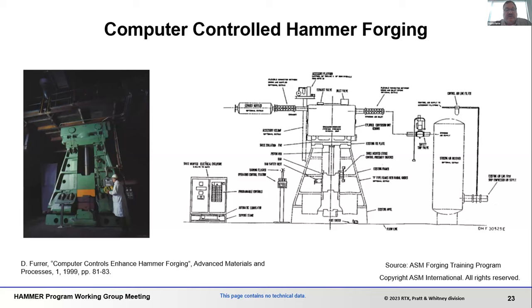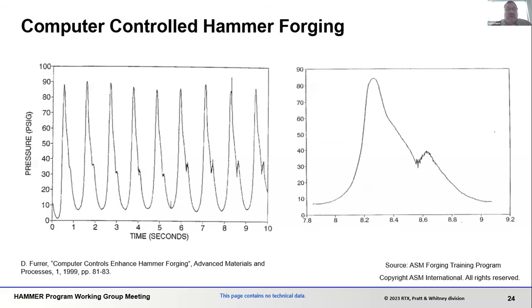But one of the main reasons is to control temperature, right? So now you can start to forge and incrementally control the amount of adiabatic heating and the amount of heat that you're allowing to release through the tooling and structure. This is a way to now link it to models to come up with a hammer forged product with a very, very controlled microstructure and final mechanical properties throughout the volume. In addition to controlling the hammer, sensors are being put all over the hammer itself.